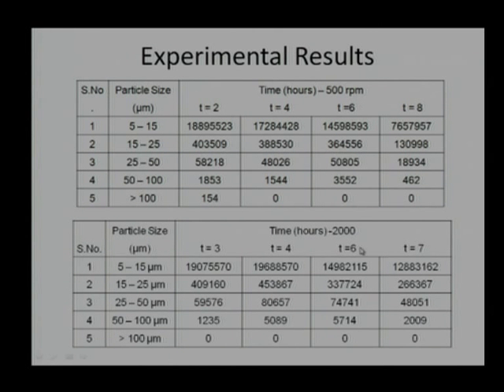Same thing was done for 2000 RPM also. What we find again is the same thing, that the number of particles is decreasing, except for this case. The number of particles is decreasing in the range from 5 to 15 micron, and there is no particle which has a size greater than 100 micron.